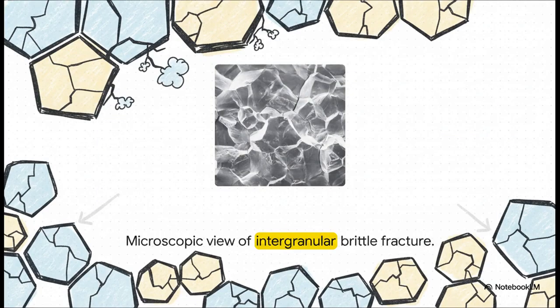Alternatively, we sometimes run into this. An intergranular brittle fracture. Notice how totally different this looks? Instead of slicing right through the grains, the failure sneaks around the three-dimensional boundaries of the grains. This usually pops up when some external process has chemically weakened or embrittled those boundary regions, essentially turning them into the path of least resistance for a runaway crack.